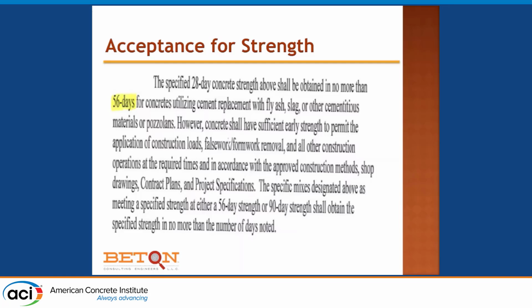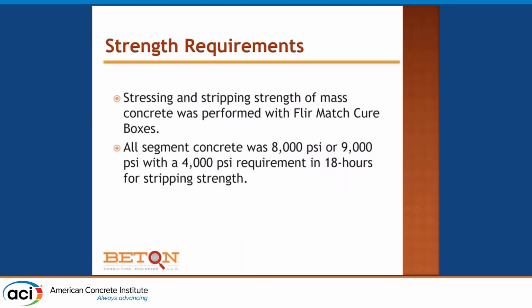And it's pretty straightforward. The contractor read this and said, well, that's nice, but my transfer girders, the top of these piers, 85 feet off the river, they need to be post-tensioned in 18 hours. And in 18 hours, they only need to be 4,000 psi. Now, they need to be 8,000 psi. You've got all 56 days to wait for that. That's fine. 4,000 psi in 18 hours. And the segments will be the same.